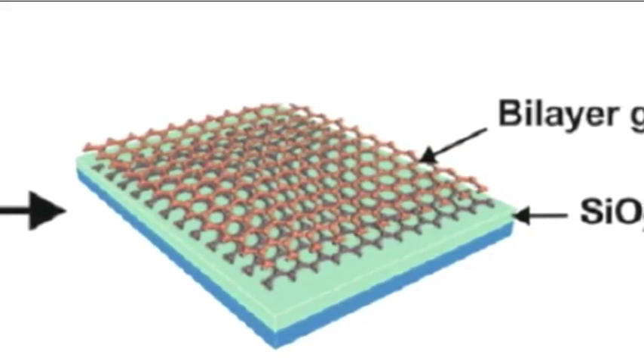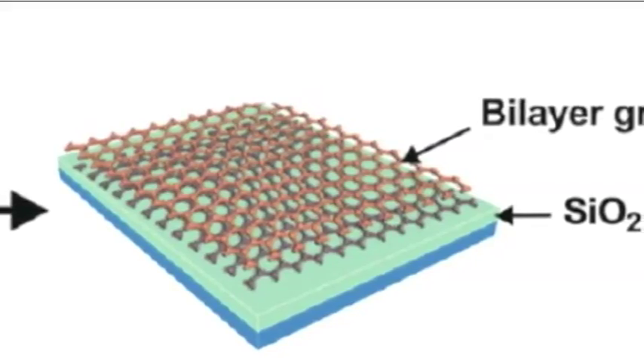There are newer ways now of directly growing graphene on an insulator, so you don't have to do a roll-to-roll transfer. You can directly grow it without having to transfer it, because transferring graphene can be somewhat problematic — it's like dealing with plastic wrap, a thin sheet of plastic wrap, but this one is only one atom thick, so it becomes even much harder. So if you can grow directly where you want, that would have an advantage. Still, the problem with the direct growth method is that you have to reach temperatures of a thousand degrees, which are too high for most polymers, but okay for insulating substrates like silicon oxide, silicon nitride, or boron nitride.